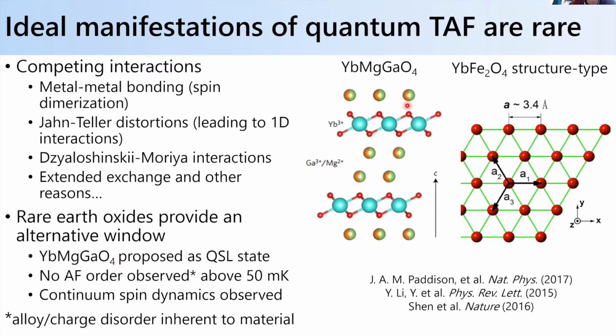And so here's just a picture of the lattice of the material. It's comprised of planes of ytterbium 3+ ions sitting in the center of oxygen octahedra, which are edge sharing. And then these are separated by magnesium and gallium spacer layers. So it's a 2-dimensional material. And the triangular lattice in the plane is a perfect R3 bar M structure.